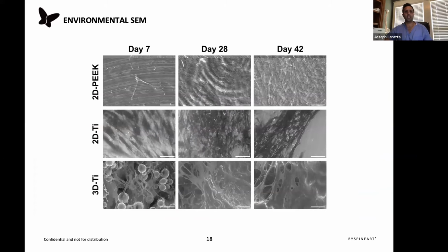When we look at the scanning electron microscopy for two-dimensional titanium, we see a similar type of thing. At day 7, you see a confluent organization of cells, but then somewhere between day 7, day 14, day 20, the cells begin to pellet in the center, and then by day 42, the pellet that remains in the center starts to proliferate, but everything on the side doesn't. There are some cells that remain attached to the titanium, probably a few, and those are proliferating, but most of the cellular attachments had been disengaged by day 42.